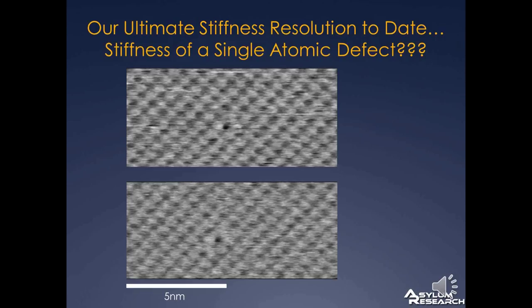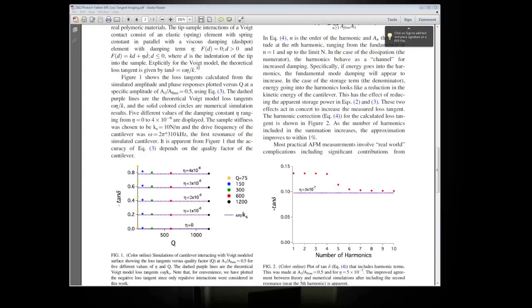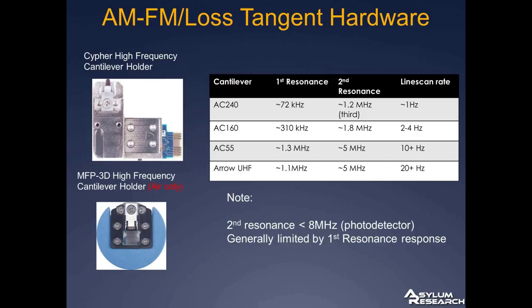And again, this is combining a few questions, but several of you asked whether you can do this on your current Asylum Research hardware. Good question. The only requirement for current MFP and Cypher users is a new high-frequency cantilever holder. The high-frequency cantilever holder is required simply because for FM mode, you want the transfer function between the drive piezo and the cantilever to be as smooth as possible. If you have a lot of structure in that, meaning resonances and anti-resonances in the drive, then you get a lot of coupling between the amplitude and the frequency, which causes a lot of artifacts. So these new high-frequency holders are very smooth and work for high frequencies.